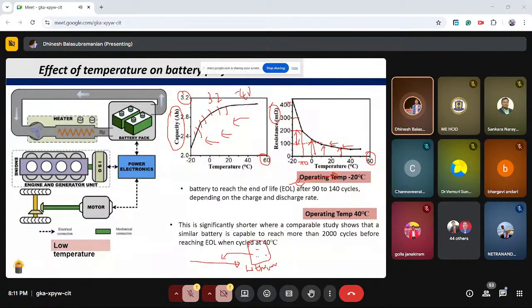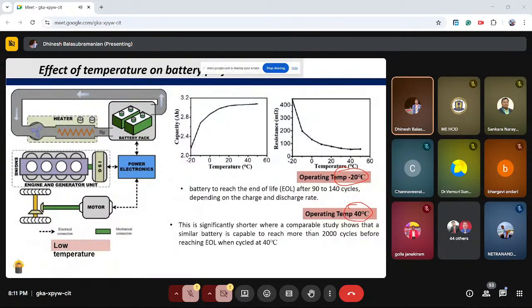And what would happen when you try to operate at two different temperature ranges, as I have mentioned here. When you look in detail, when you operate at -20 degrees Celsius versus a higher temperature of 15 to 35 or 40 degrees Celsius, there is a significant difference. The comparable study shows that a similar battery was capable of reaching close to 2000 cycles, but now it is 5000 to 7000 cycles for effective battery operation, before its end of life, which is when the total cell capacity should not be less than 80% when cycled at 40 degrees Celsius. But when you operate the same system at -20 degrees Celsius, the end of life comes in just 90 to 140 cycles.